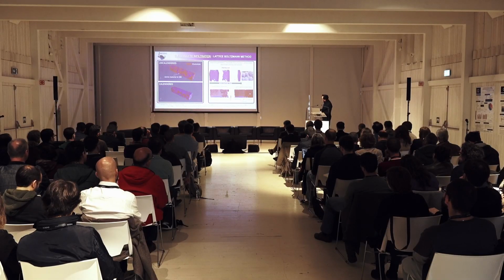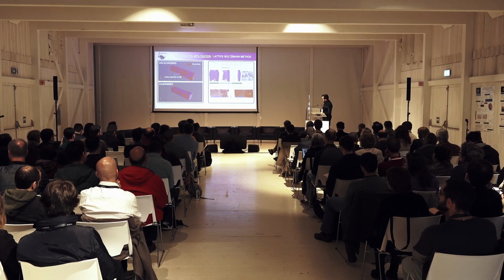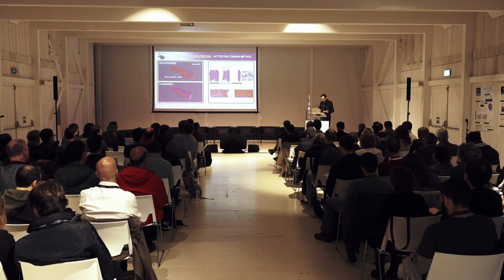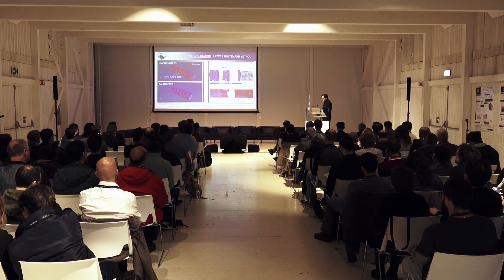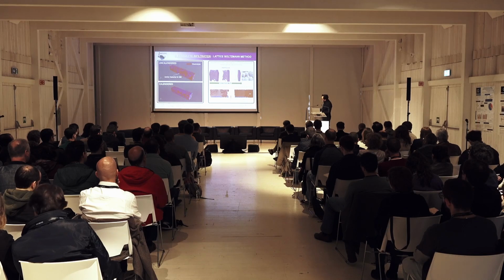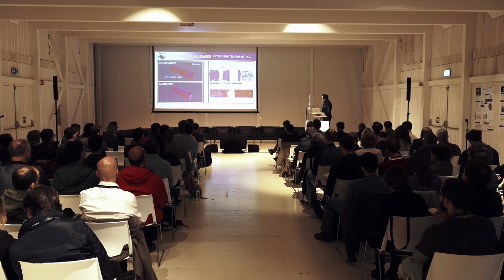And the reason is that the two electrodes here are made of different active material chemistries with different particle sizes. The electrodes also have different porosities and different tortuosities, like the separator. And therefore, the electrolyte infiltration is highly heterogeneous. That means that you will not fully fill all the pores with liquid electrolyte. And this is also a problem in industry. Okay? Industry wants to homogenize as much as possible the electrolyte infiltration of the cells, right?